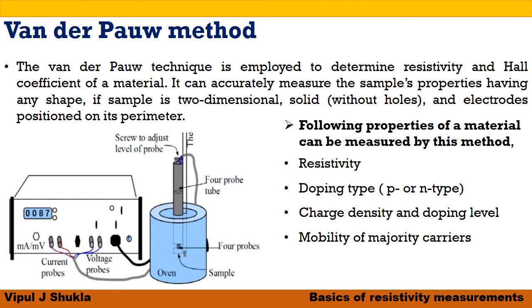Potential drop across the two probes is measured and the gap between them is taken as the sample length. If the probes are not point contacts, the true value of probe distance is the gap between the centers and not the shortest distance between them. The 4-probe method equally applies to single crystal or bulk samples and can determine their resistances. Current flows through outer contacts near the sample edges and potential difference is gauged across inner contacts.